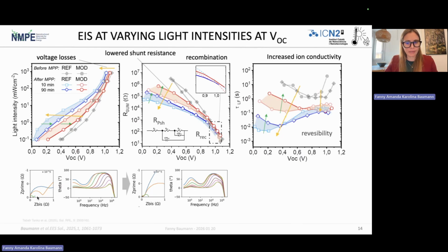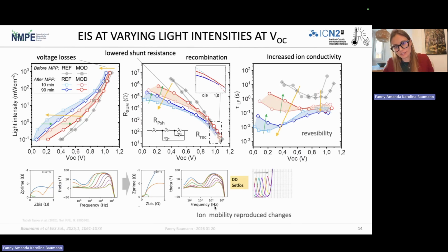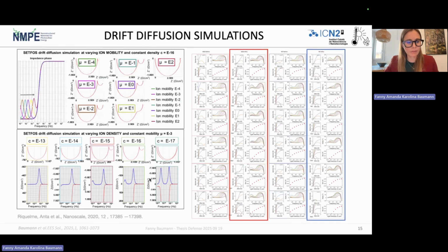And what we did is we compared the shape of the impedance spectra, and we could see this changes with, and we could reproduce them using Setfos. And what we saw was that we could reproduce changes much better by using changes in ion mobility compared to ion density. So what we did was we got a lot of help from Professor Juan Anta, who had recently published a paper with adequate parameters that we could copy in order to get more reliable simulations quite quickly.